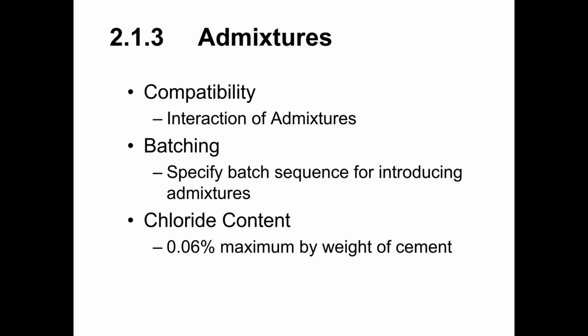Generally, again, your admixture supplier will be the best source of information with regard to when each particular type of admixture should be introduced into the mixing process. If we have two admixtures that are known to interact with each other, but we introduce them into the mix at separate times, then we may be able to avoid that interaction and still use those admixtures together. So make sure that you're in close contact with your admixture representative and getting advice from them with regard to the sequencing of your batching process for the admixtures.